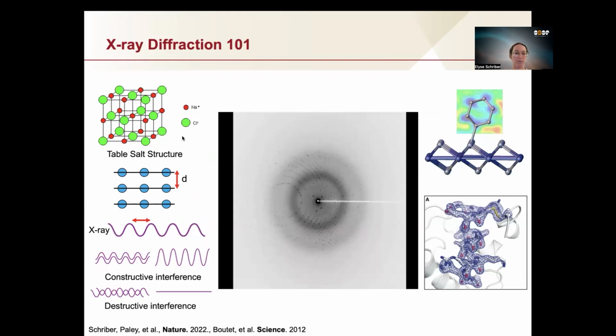So in this case, we have an example of table salt, sodium chloride, and the table salt structure itself, at least the repeat periodic array of the table salt structure, acts as its own double diffraction slit when exposed to monochromatic X-ray light. An X-ray's wavelength is almost equal to the spacing between the atomic lattices, called d-spacing. And through a process of constructive and destructive interference, as the crystal is rotated at different orientations through a monochromatic X-ray beam, we start to see the reflections show up.